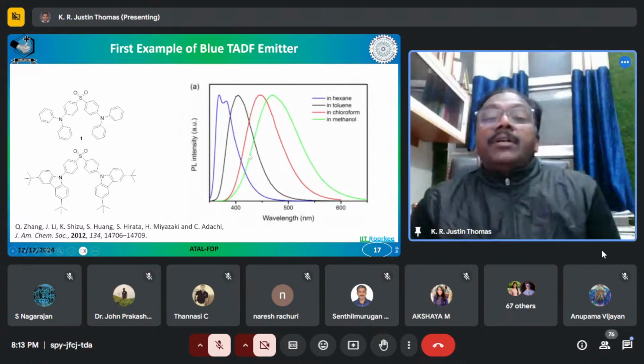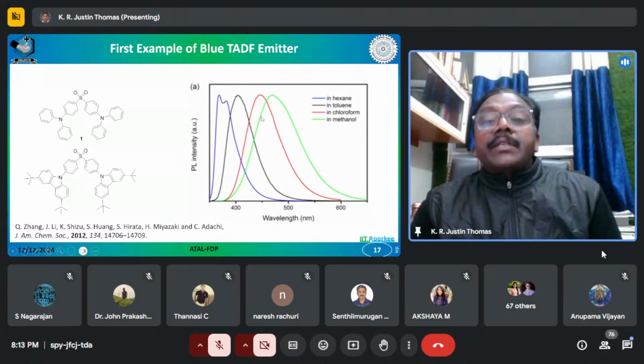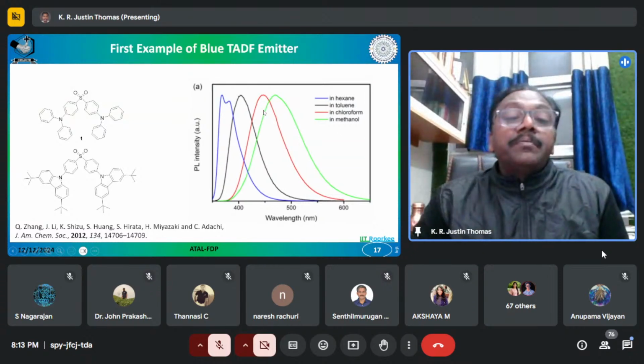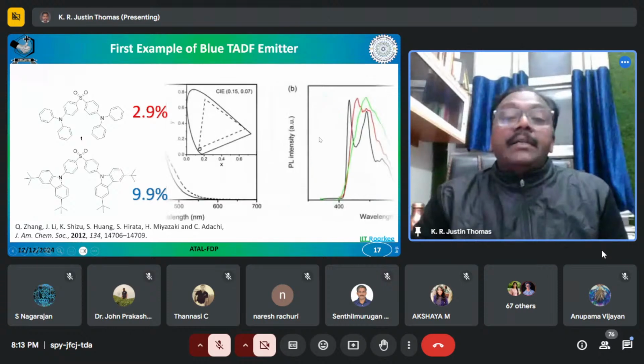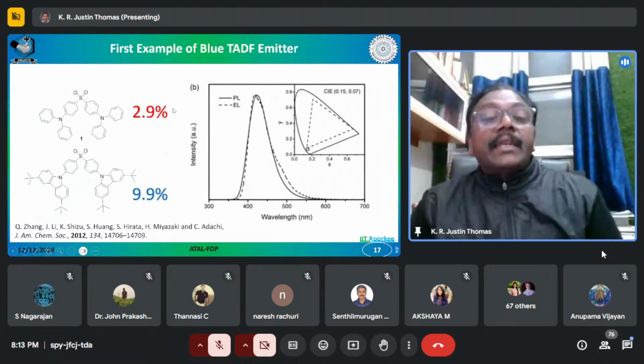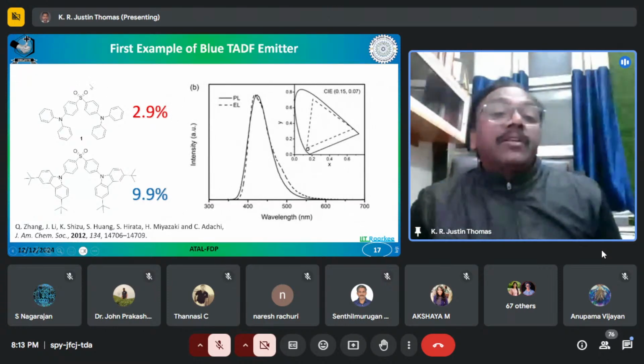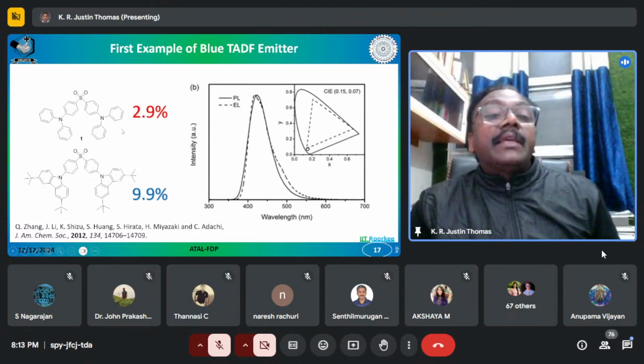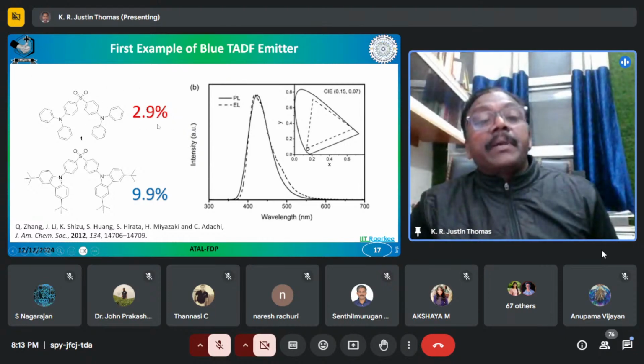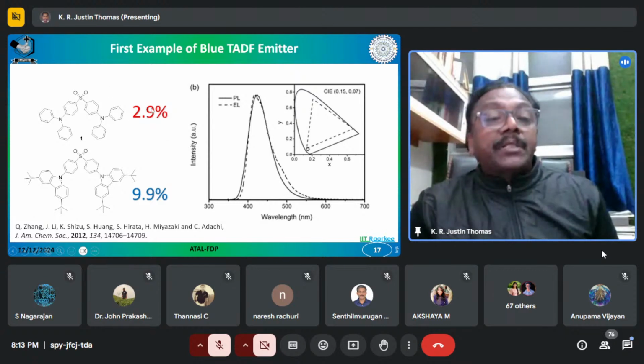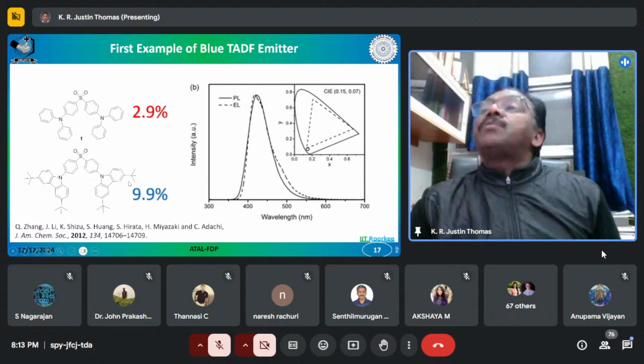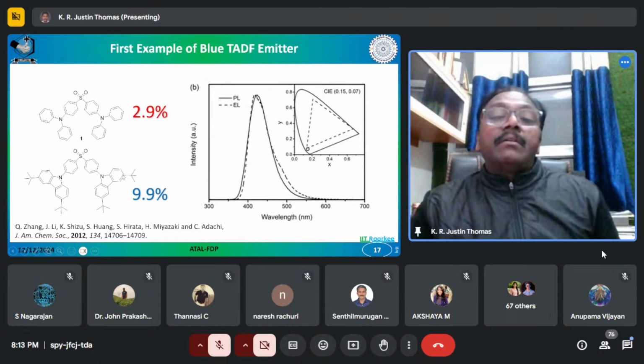Okay, so it also has a charge transfer excited state, which is solvatochromic in nature, showing solvatochromism. And you can see a great enhancement in the efficiency. This molecule has an efficiency well within the limit of fluorescent-based materials, less than 5%, that is 2.9%. And this one is showing 9.9%. This was one of the important outcomes at that time.